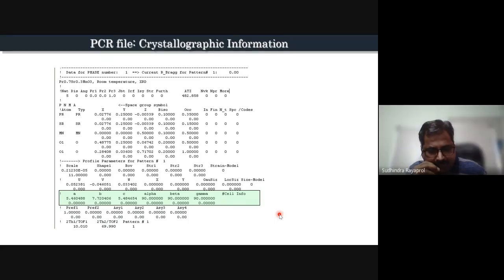The first thing is that you see if you have an isostructural compound, something which is nearby your pattern. Before you go into the CIF file or Rietveld refinement, you have to index the pattern. You either do indexing manually or you do it with LeBail fit to identify what is the space group which satisfies these conditions. If it has formed an alloy or an intermetallic alloy, then it will have certain positions, right? If it is a composite, then you have to do two-phase refinement. If a secondary phase is coming up, then you identify that phase and input that secondary phase, and then you can do a qualitative two-phase refinement and find out what is the phase fraction.